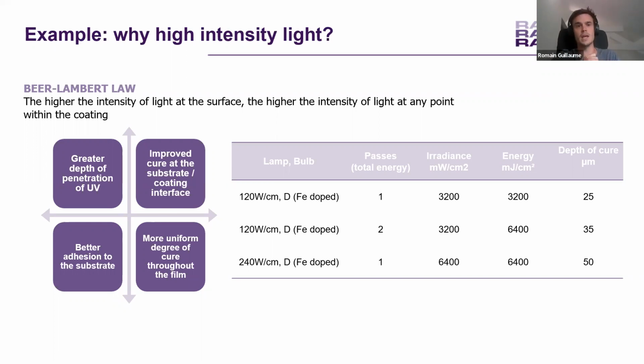That's an important question, and we know that the higher the intensity of the light at the surface, the higher the intensity of the light at any point within the depth of the coating. This has several positive impacts, like a greater depth of penetration of the UV. Thanks to that, we improve the cure at the substrate-coating interface, which is the deepest zone for the curing application. Thanks to that, we increase the adhesion to the substrate, because we have a better degree of cure close to the substrate.